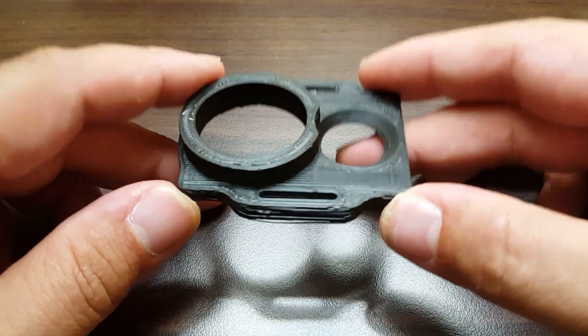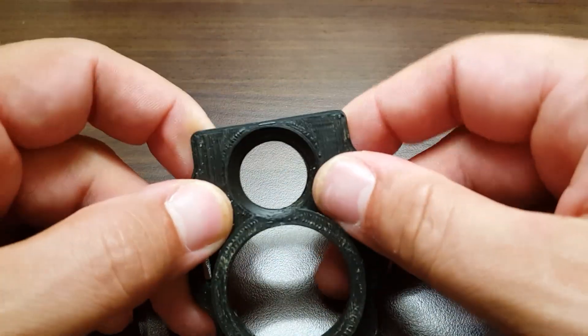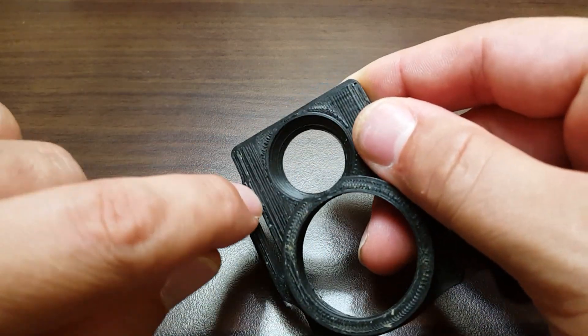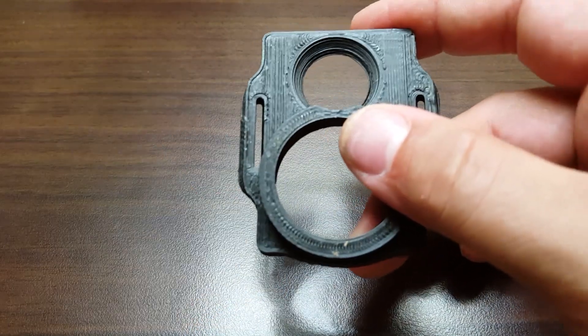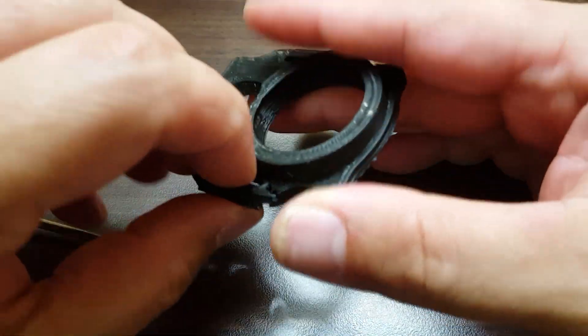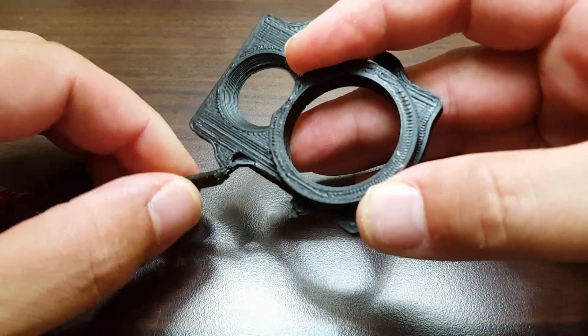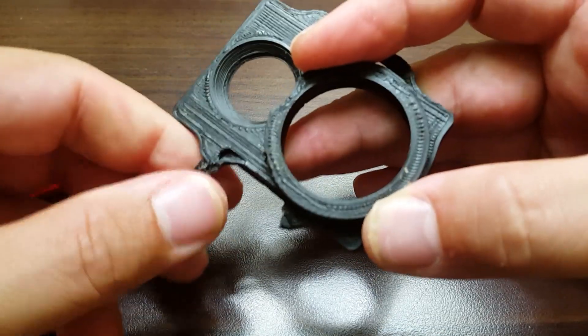But there's another downside of 3D printing, at least when it comes to mini quads. I don't know — you guys who know about 3D printing instantly know what kind of plastic this is. But when you 3D print something, it has these layers that it builds up as it prints. And so it's weak along those layers. So in a crash, this is what happens — it shatters along those layers. And this happens, it doesn't happen maybe the first time — actually I had to work harder than I thought I would to do that. Maybe it's a cumulative thing. But eventually these things shatter along those layers and they break.